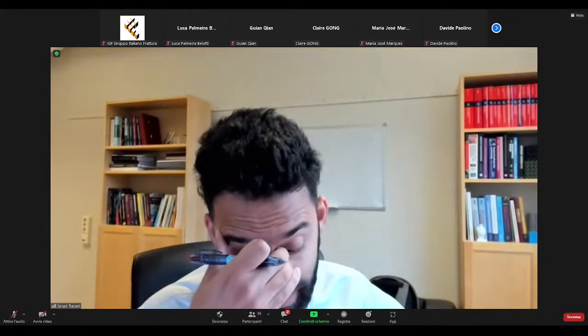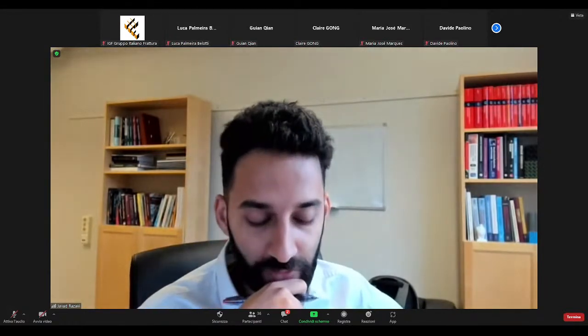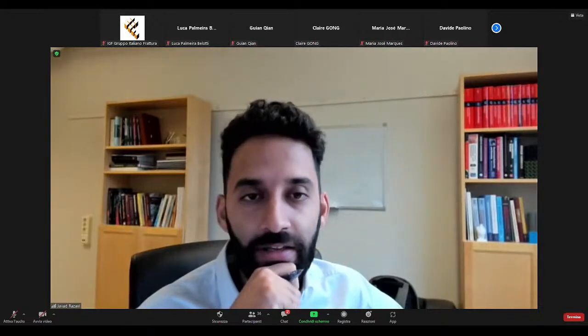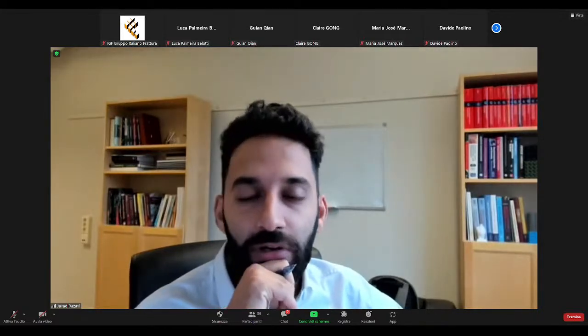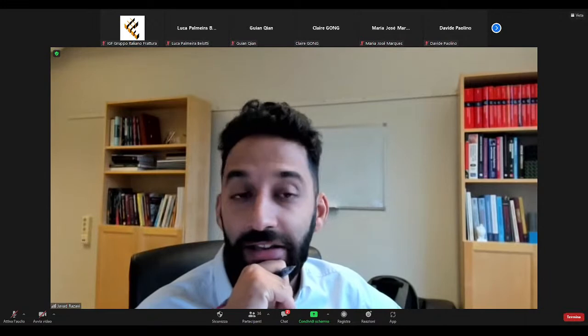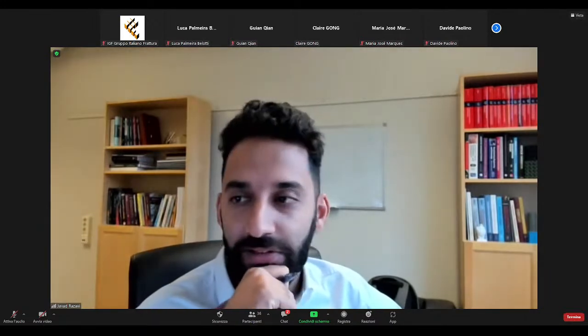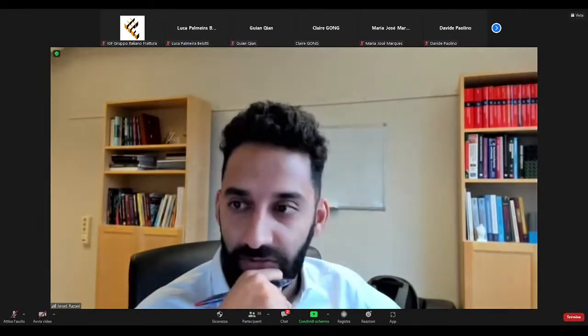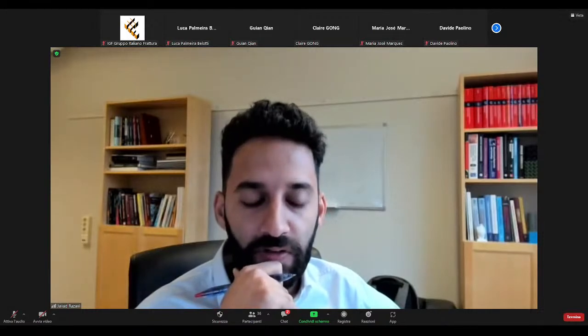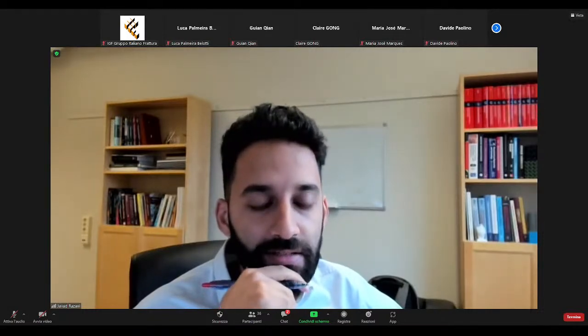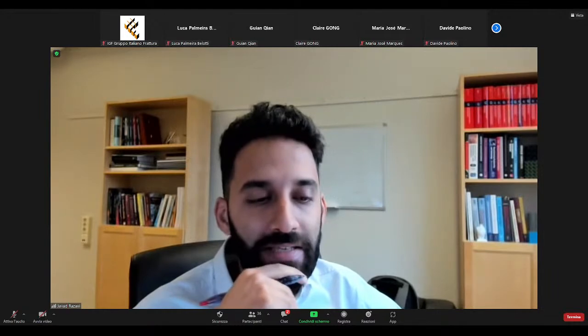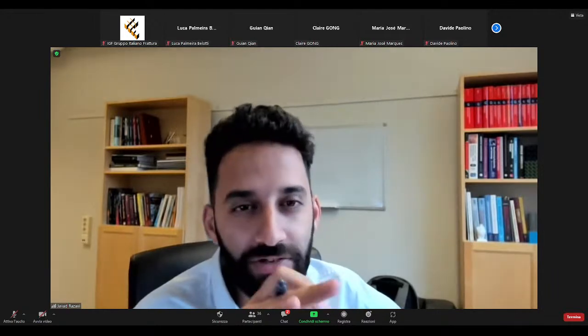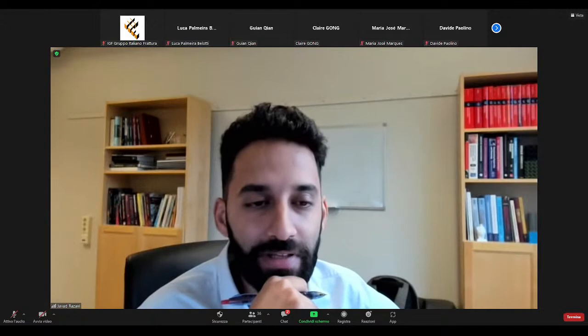So these techniques, similar to this, what we were doing before was to use indentation to create this pattern, and it was quite demanding and also locally damaging the material. So it was quite nice to see the results that you presented in your work. What I'm wondering is, what is the maximum surface roughness range approximately that you can apply this technique on?